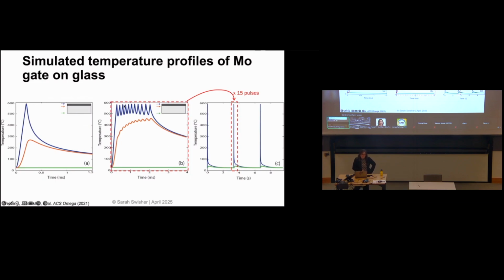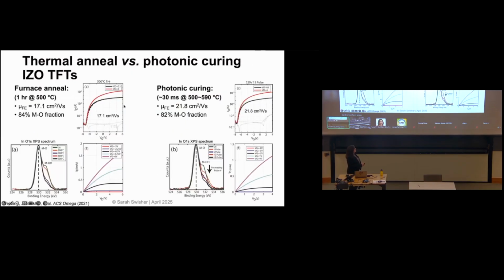So when we did that, I'll show you what it looks like compared to a control device, which is our thermally annealed devices. So on the left here, we have TFTs that were made in a traditional tube furnace. So that takes an hour at 500 degrees. And remember, that's equilibrium. So everything reaches 500 degrees. In contrast, photonic curing took only 30 milliseconds, right? And it was heating the semiconductor to about 500 to 590 degrees. But the rest of the device underneath was staying cool.